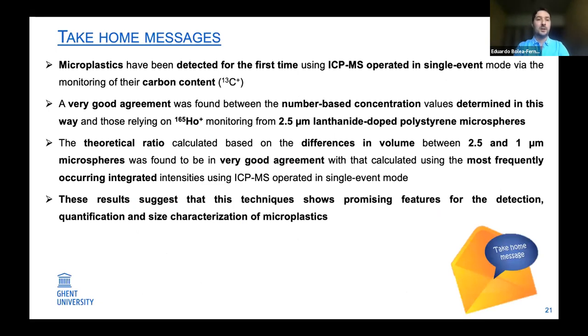So some conclusions or take-home messages. For the first time, we could detect plastics using ICP mass spectrometry operated in single event mode by the monitoring of their carbon content. In this case, monitoring the isotope of carbon 13. A very good agreement was found between the number-based concentration values determined by monitoring carbon and those relying on the monitoring of 165 holmium for microplastics doped with lanthanide elements.